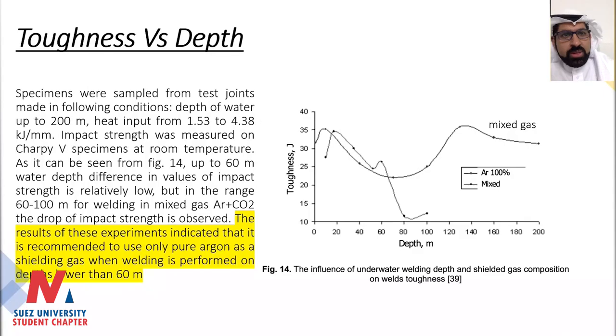Please, next. Almost done here. Also, depth and toughness. This is another study that shows that if you are doing underwater welding, up to 60 meters, it's fine to use 100% argon. After the 60 meters, then you're going to have a high drop in your toughness. Then you have to use mixed gas, which is argon plus carbon dioxide. That will stabilize your toughness in your sample.